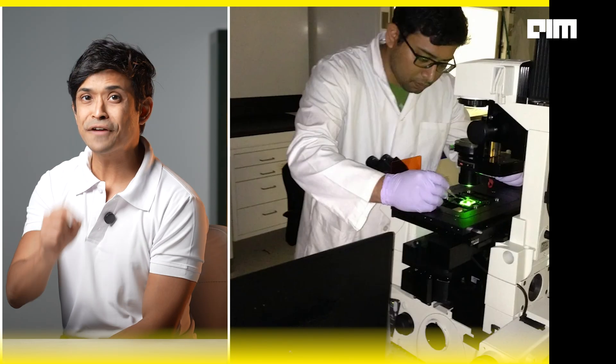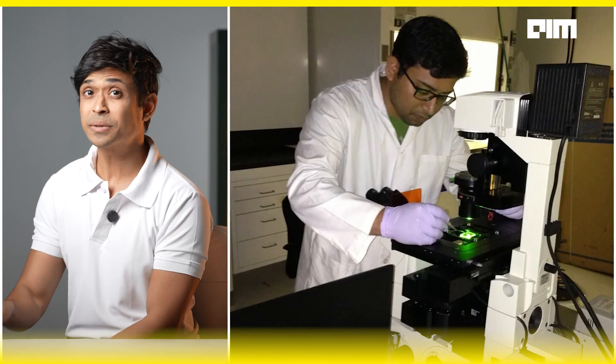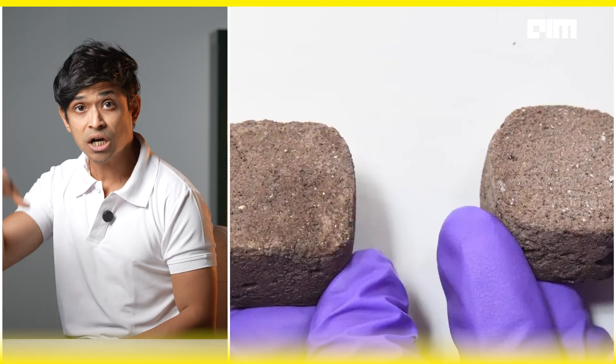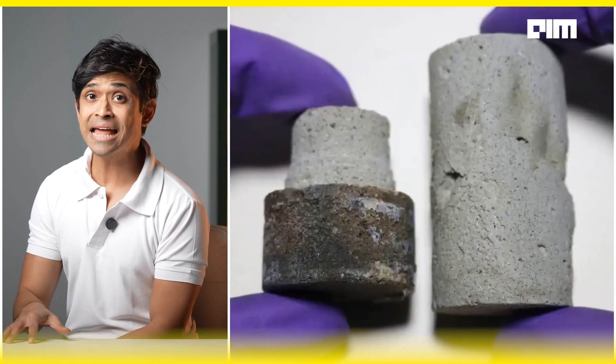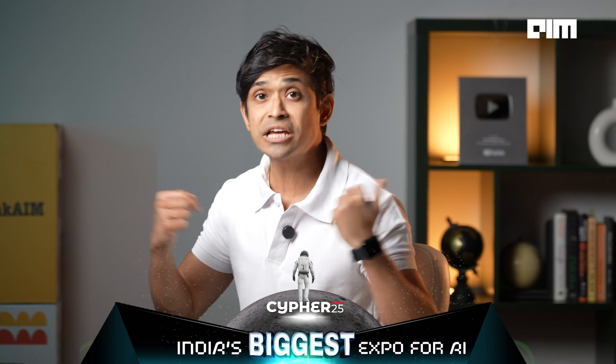To fix cracked bricks without sending spares from Earth, IISc developed a bacterial repair system. Researchers introduced cracks in sintered bricks on Earth, then poured in a slurry of S. pasteurii, added guar gum, and then lunar soil simulant. Over time, the bacteria filled the cracks with calcium carbonate, almost acting like a biological glue — restoring brick strength and resilience.